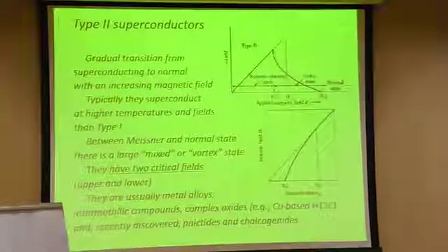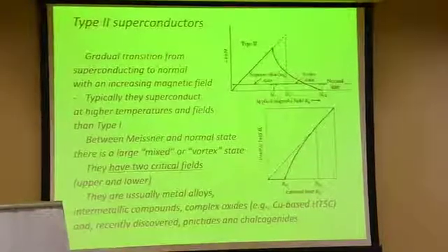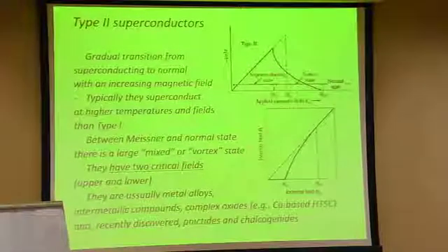It is very important to look at the following thing. We still have something which is called the thermodynamical critical field. That thermodynamical critical field will be found when we do the calculation of the free energy between the normal state and superconducting state, and this Hc is actually the square root of Hc1 multiplied by Hc2. We cannot see it in this type of measurement, but the thermodynamical critical field still exists also in type 2 superconductors.